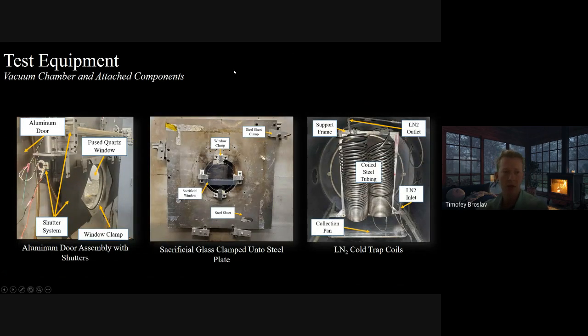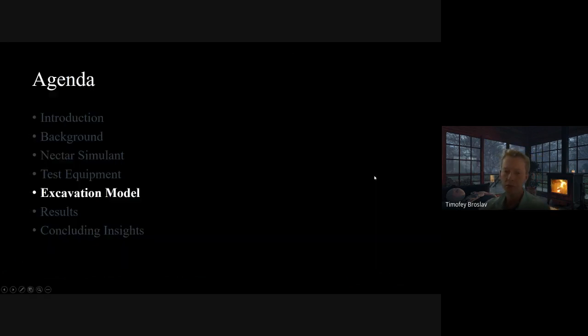Other vacuum equipment and test equipment includes the aluminum door assembly, the shutters that I talked about, as well as the sacrificial glass to block any, I would say, debris from hitting the main 13-inch fused silica glass, and the liquid nitrogen cold trap coils.